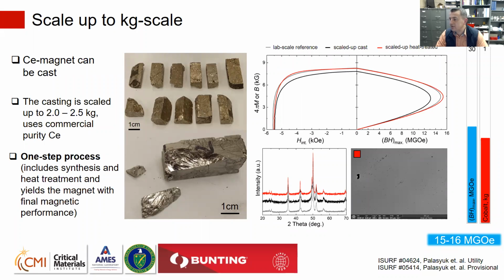The squareness of the second quadrant curve of the casting suggests that you have a reasonable degree of alignment. Exactly. Are you chill casting? No, I am not chill casting. It's just melting in the alumina crucible. But alignment, you are absolutely correct, is coming from the microstructure, which is absolutely anisotropic and developing perpendicular to the easy axis.